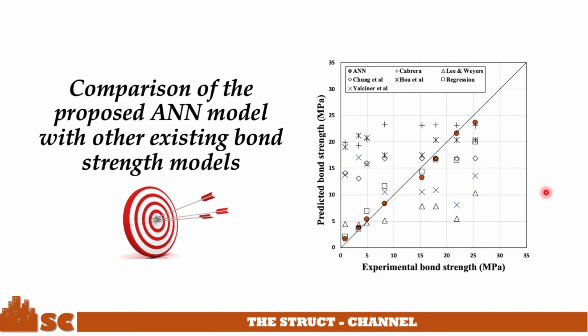The proposed ANN model, on the other hand, was able to exhibit robustness in predicting bond strength values, as shown in this figure. A close fit can be seen from the graph with an R value of 0.986. The limitation of the hidden nodes and the early stopping adopted in the development of the model worked so well to improve the generalization of the model. The average observed error in the prediction results was 17.22%, with maximum and minimum errors of 53 and 0.78% respectively.